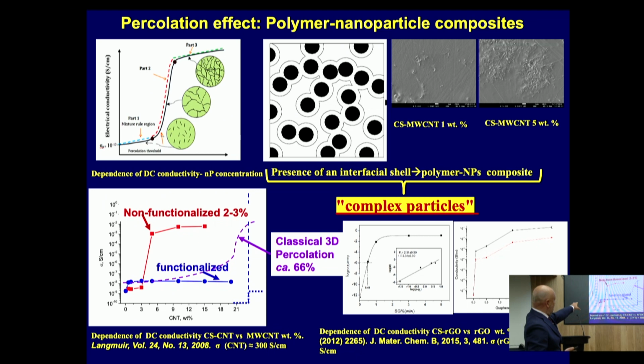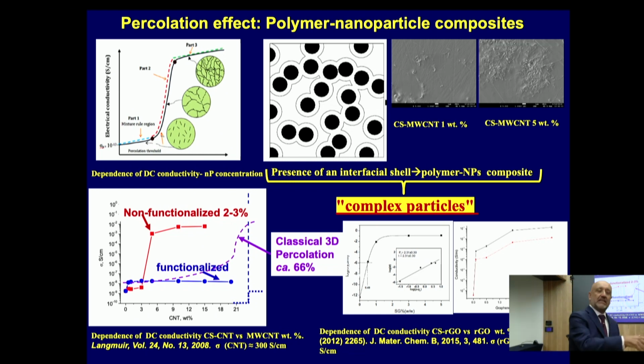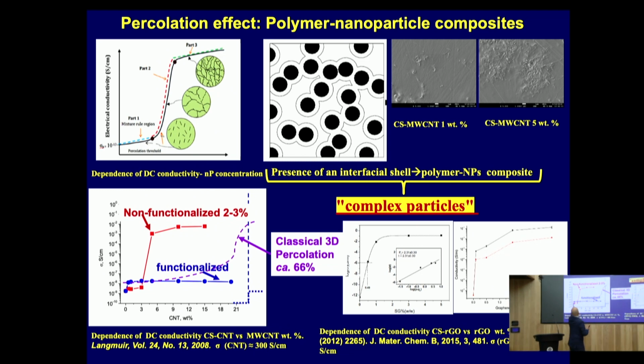look at the blue dots, it's a functionalized material. Many people do acid, basic treatment, laser ablation, radiation to erode the nanotubes and expose double bonds instead of just single bonds, carboxylate, hydroxylate, or induce some defects. If you have the proper polymer matrix, the material becomes non-conductive, even though you have used carbon nanotubes, which are a highly conductive electrical material. And this could be deceiving, but we have proved that before. So for instance,